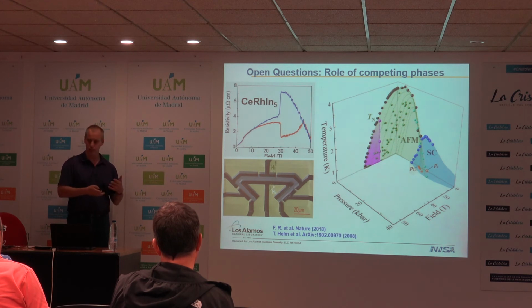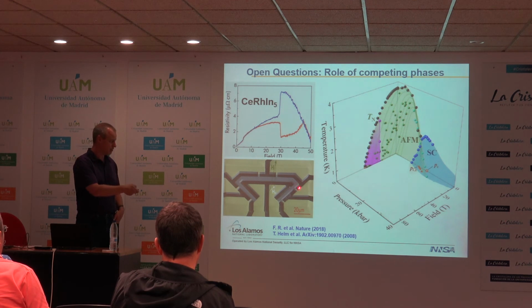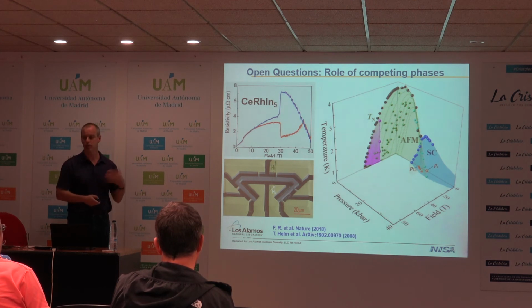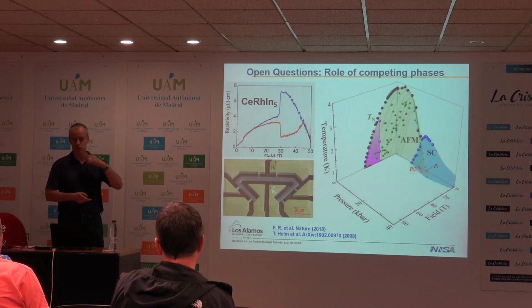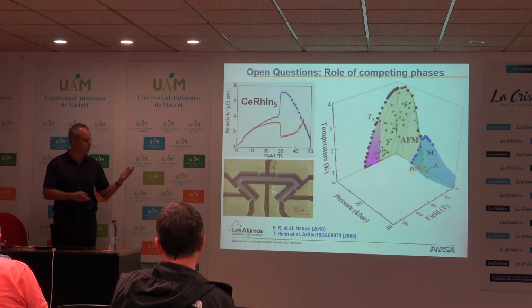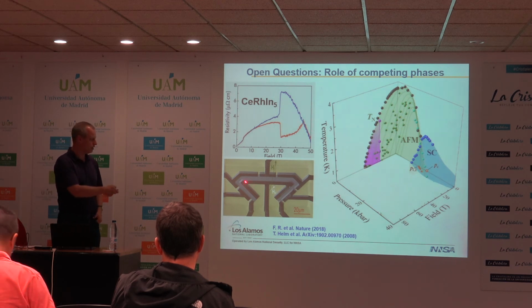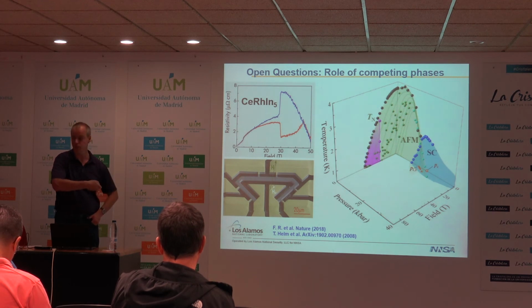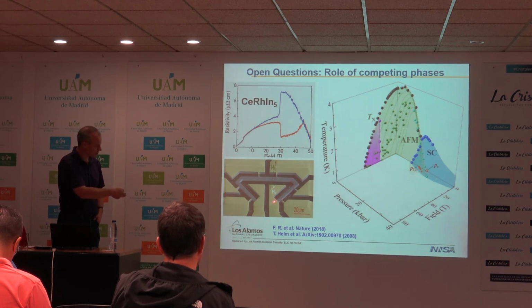So you actually want to increase the overall resistance in the sample, and that was the motivation for making this FIB structure, as well as the fact that you have large eddy current heating if you're doing this in pulsed magnetic fields. And so we wanted to go to large fields. In Los Alamos, we can go to 65, maybe even 100 Tesla. And so the eddy current heating is a huge problem when you want to sit at temperatures of order 1 Kelvin or less.